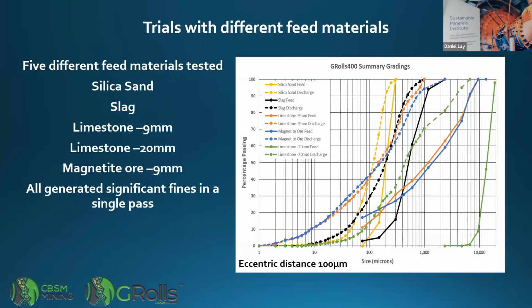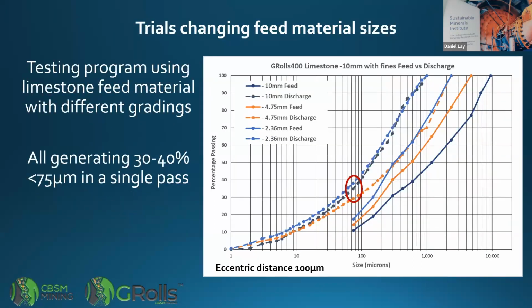So then we looked at changing the feed material sizes and see how it improves. By going coarser and coarser material, we're still getting a very high fines generation. That's up to 10 mil feed. We're getting very similar material coming out the bottom end.